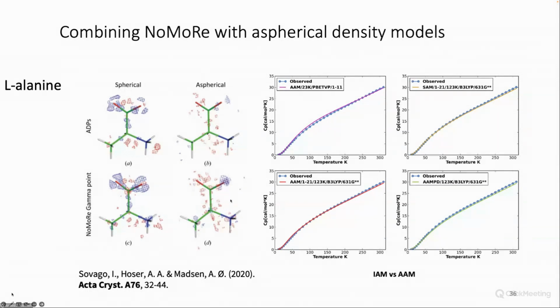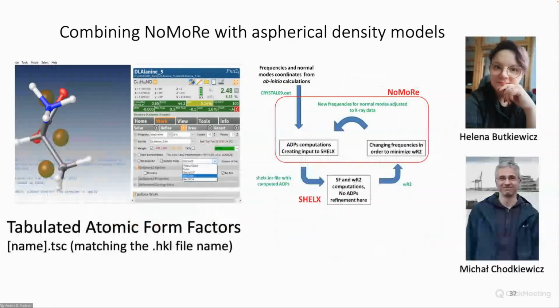So there's still some room for improvement, and the latest idea we have is to try to use other types of aspherical density models and to use them on a larger range of systems to more thoroughly study this phenomenon. And we have had help here from Helena Butkiewicz and Michał Chodkiewicz from the Warsaw group, in order to create a version of this normal mode refinement where we go away from using the SHELX program into using something called CalcFCF, which is a small program that Michał has made for us, which is based on these form factors that we can get, for example, from the DiSCaMB server or from different other approaches like the Hirshfeld atom refinement method, which are now all available in the OLEX2 suite of programs.